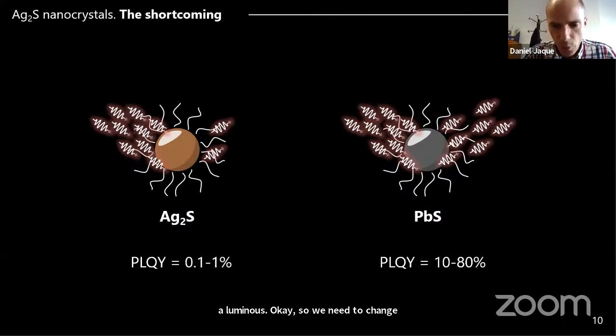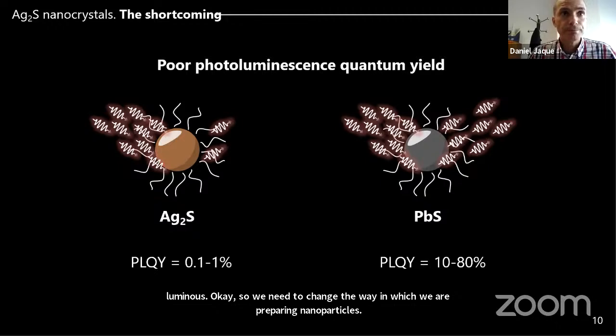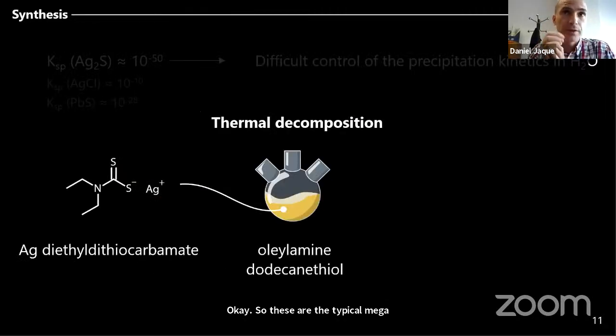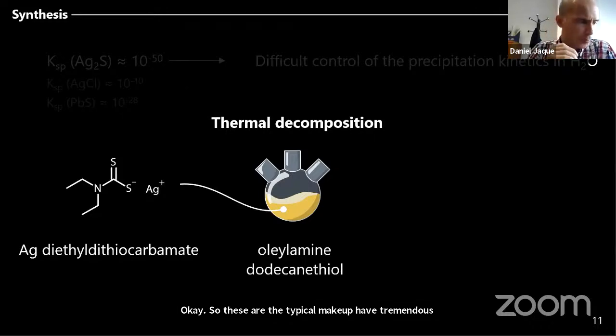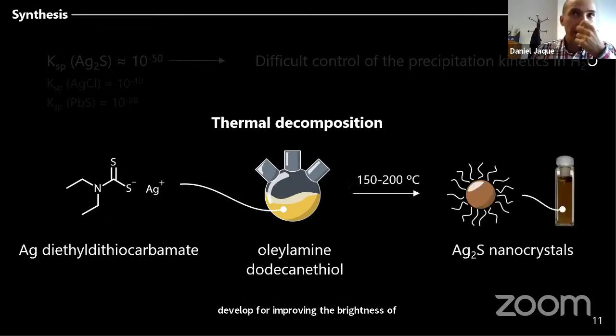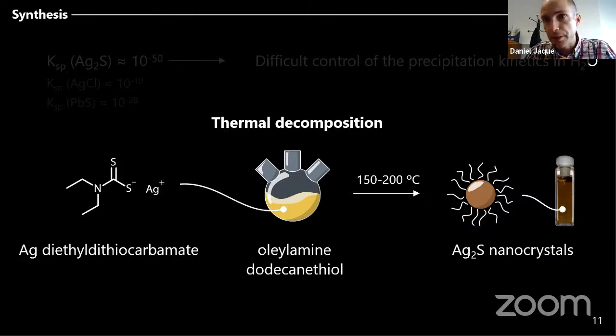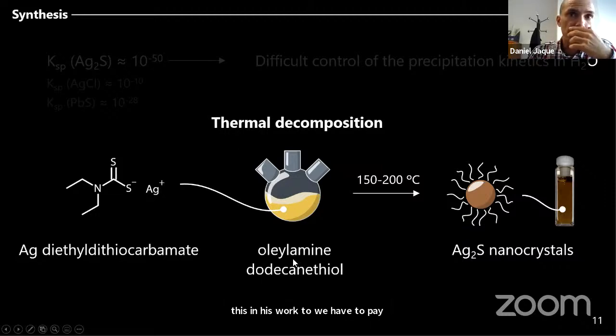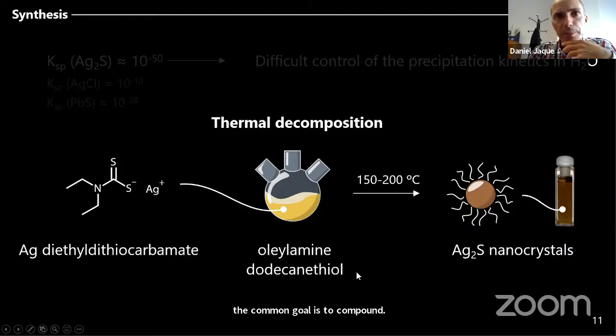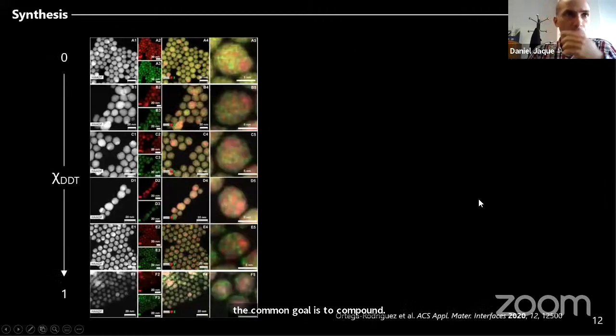So we need to change the way in which we are preparing the nanoparticles to improve the brightness. This is the typical method of thermal decomposition, the method that we are trying to develop for improving the brightness of these nanoparticles. The idea is to modify this traditional method of synthesis to improve the quantum yield of silver sulfide nanoparticles. In particular, in this work we have two precursors for thermal decomposition, oleylamine and dodecanethiol, and we are going to work by changing the ratio between these two compounds to try to improve the properties of the silver sulfide nanoparticles.